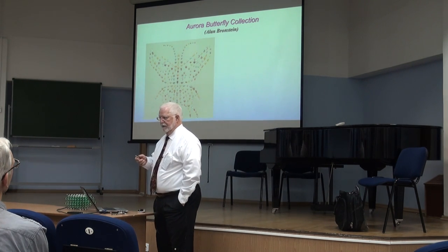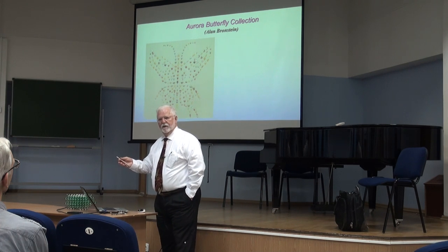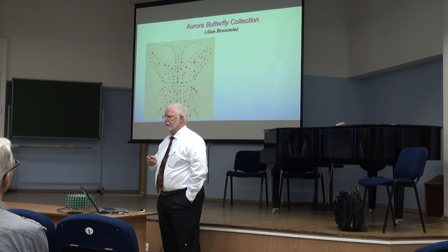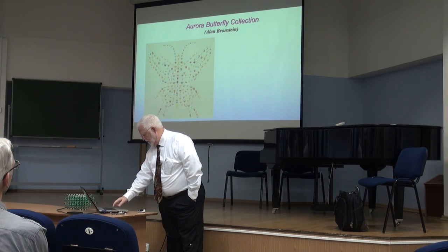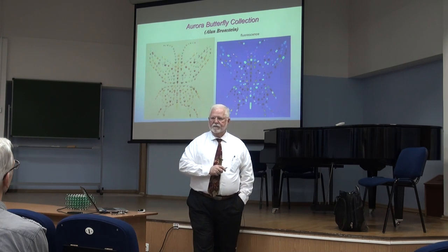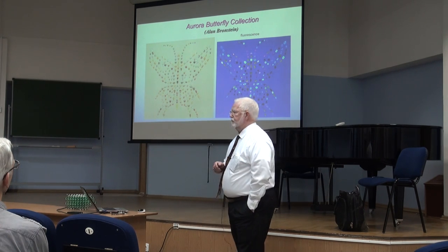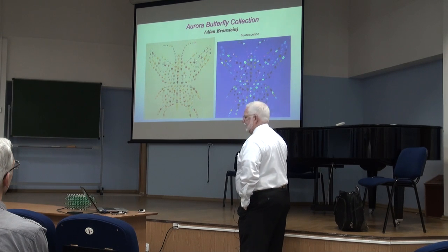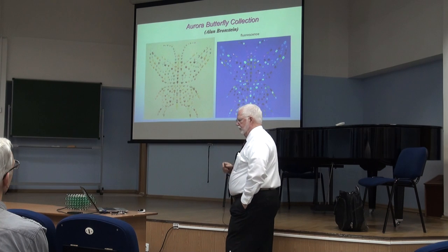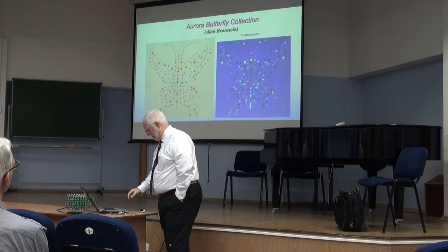The color in most pure minerals is formed by either defects or impurities that are trapped in the mineral. And in fact, if you illuminate this with an ultraviolet light, these colored diamonds all fluoresce, and they fluoresce different colors, again reflecting the fact that there are defect states and impurities inside those diamonds.